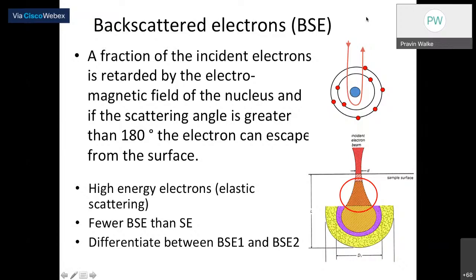And if the scattering angle is more than 180 degrees, then the electron can easily escape from the surface, right? It will just come and get deviated by the electromagnetic field and come out. So this is how we can get the backscattered electron. Those electrons did not interact much and then come back from this region, which is this one here.